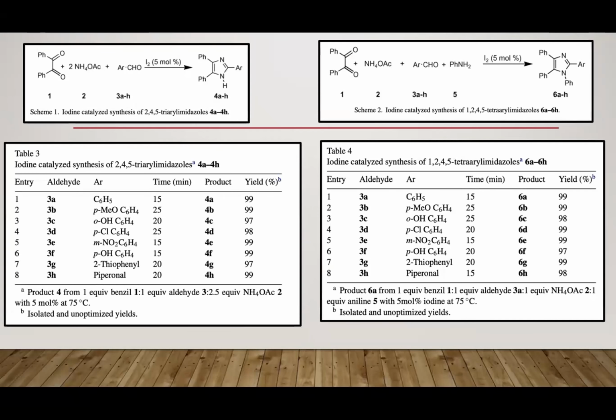So these are the two schemes, and we synthesized various imidazoles by varying the aryl-substituted aldehyde. When you look at table 3 and table 4, the substituents are of different nature. We used electron donating as well as electron withdrawing groups. Among the various products obtained, the result was significant for both types of substituents. So it can be observed from table 3 and table 4 that the process tolerates both electron donating and electron withdrawing substituents on the aldehyde very well. The aryl group substituted at different positions of the aromatic ring has not shown much effect on the formation of the final product.